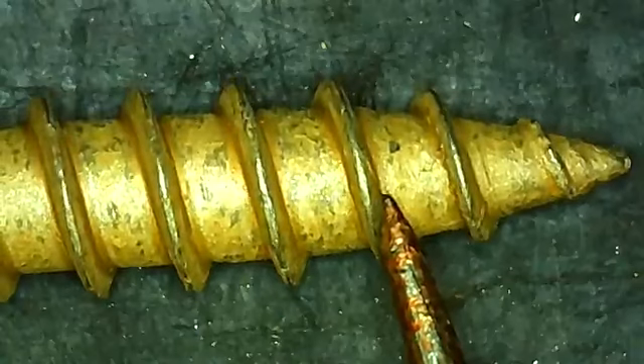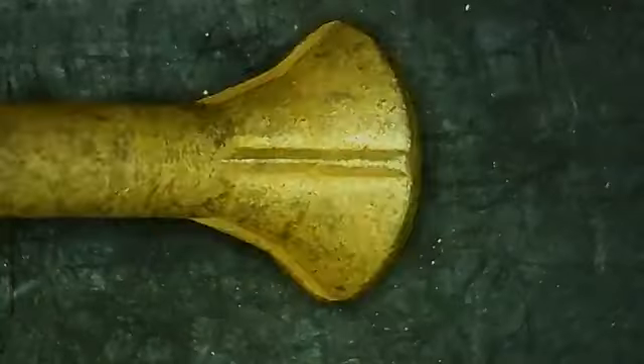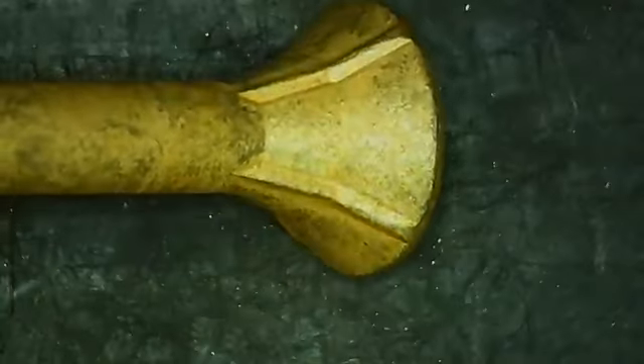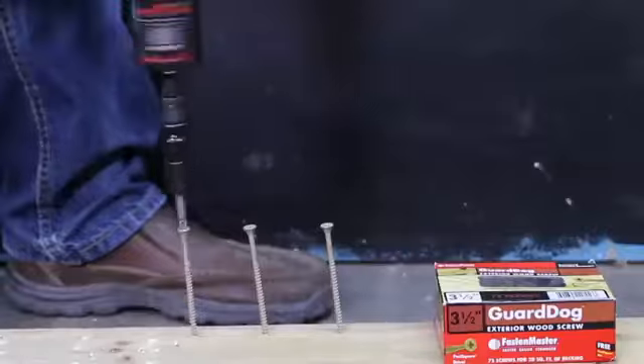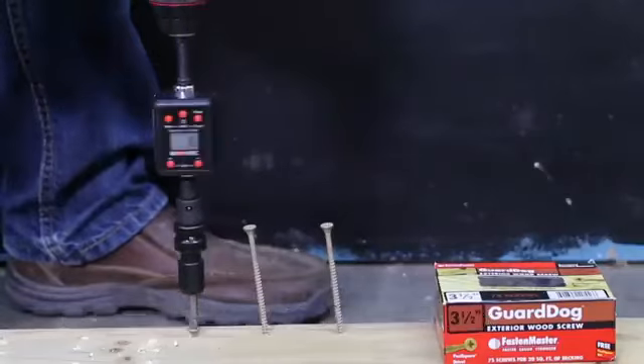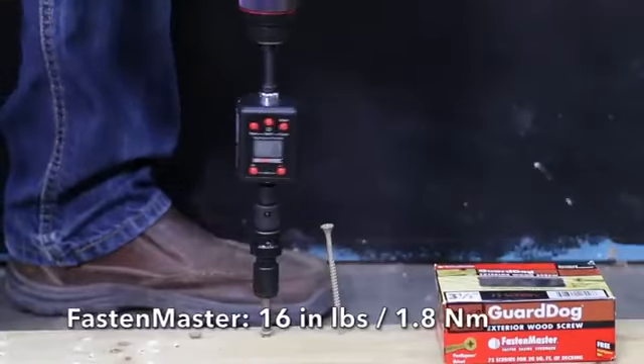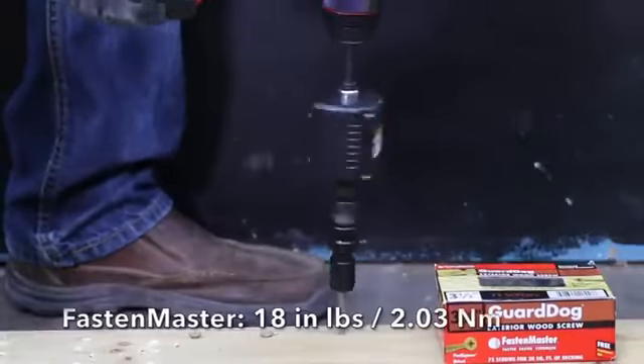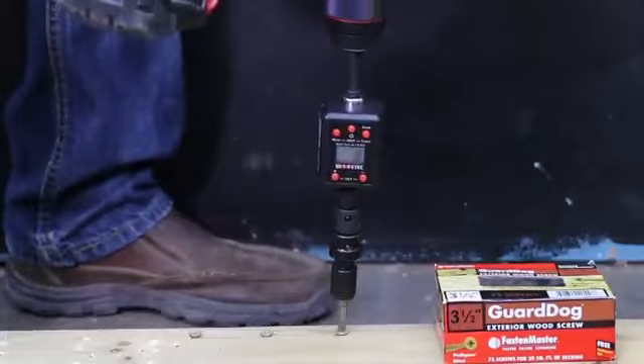A close look at the screw, and there appear to be some chips in the coating. The FastenMaster Guard Dog is made in Taiwan. 8.16 grams for the Guard Dog. 16 inch-pounds to drive the first screw, and the second screw is also right at 16 inch-pounds. 18 inch-pounds on the third screw, for an average of 16.7, the most yet of all the brands.